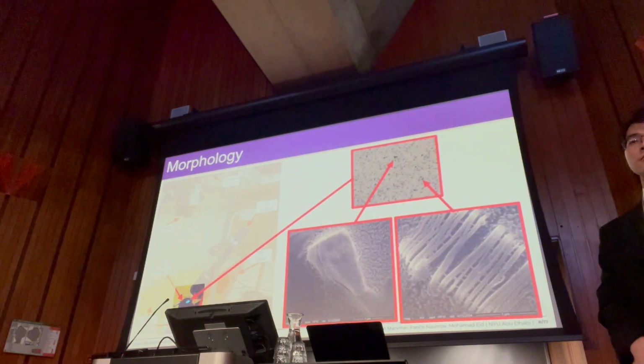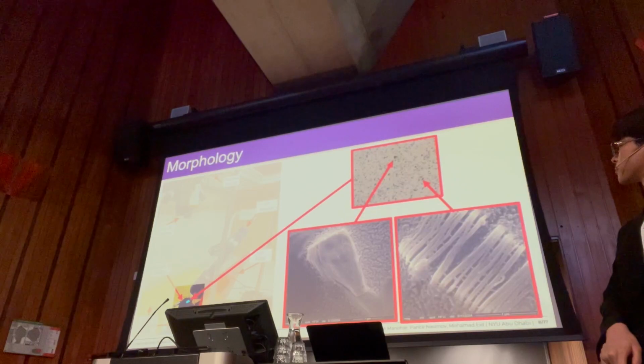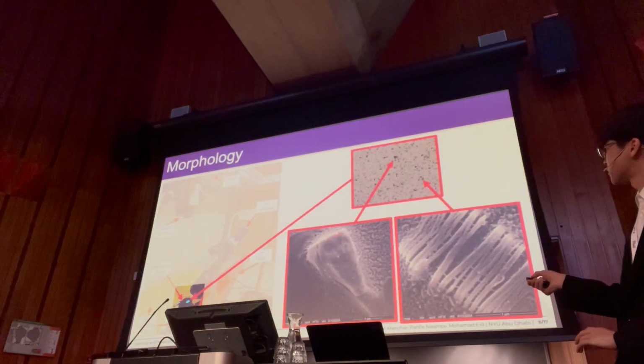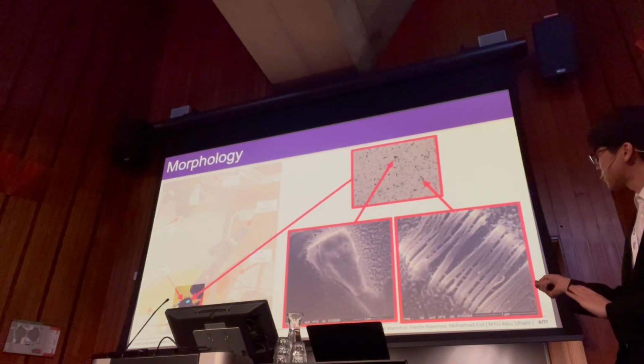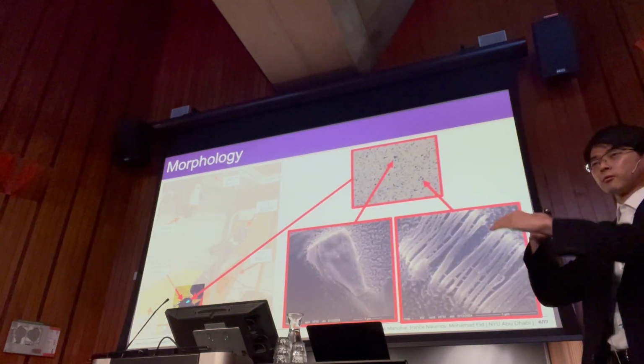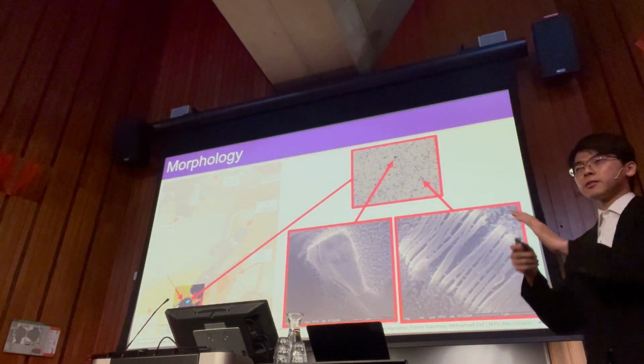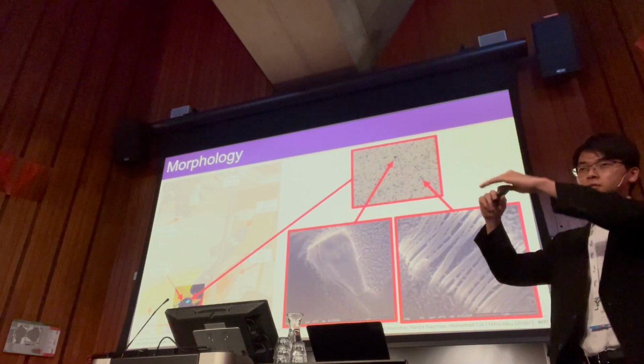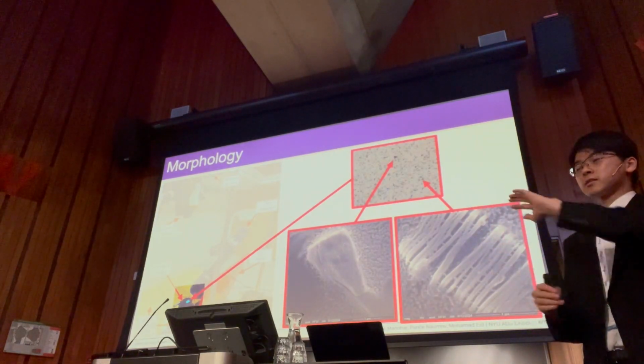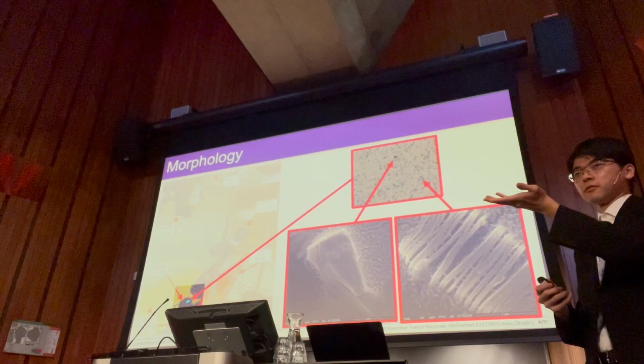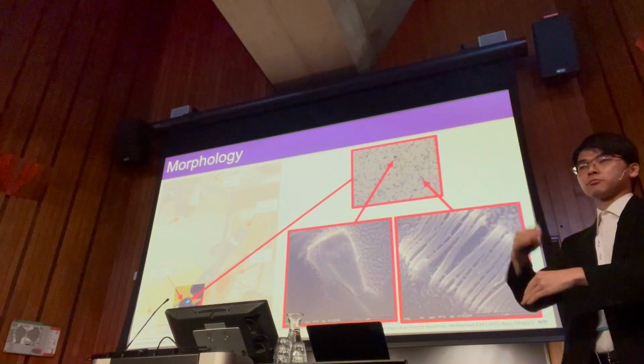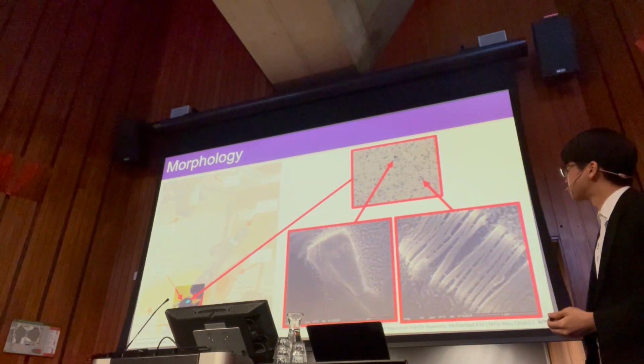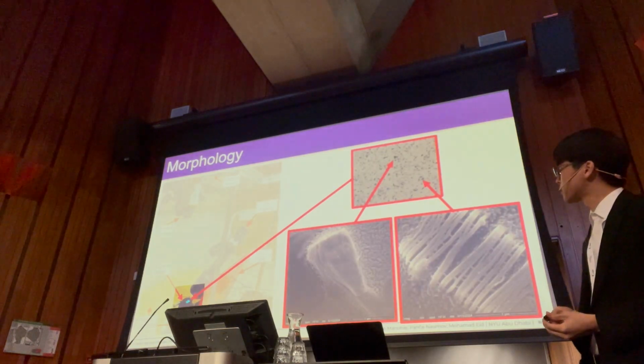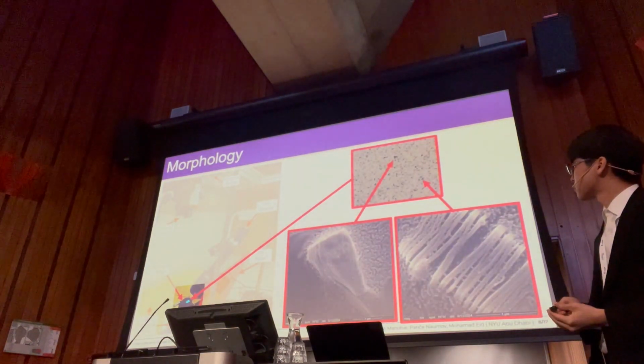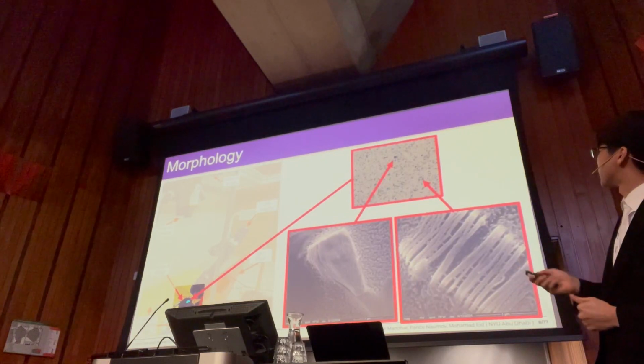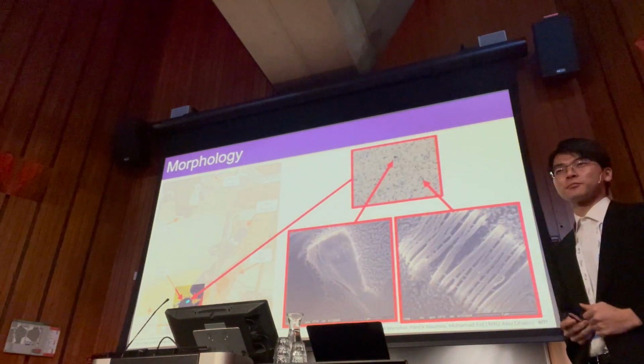True. So that could also be the case. We didn't have the chance to make a cross section image yet to see what's going on, but it could be the fact that yes, while during the fabrication it was only 10 minutes long, MXene could have condensed on the bottom, because these films do have directionality. If I flip the film, it does still actuate in the same direction, which is interesting. So that could be why. And the other reason could be, I think I blanked out, but we can discuss this more later.